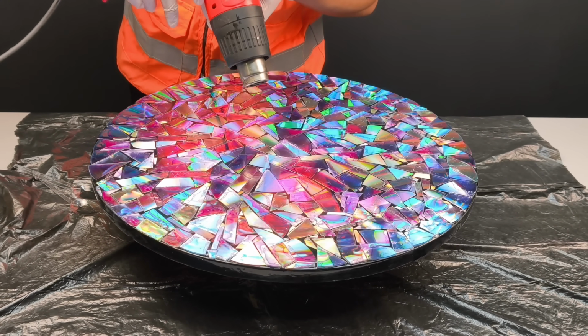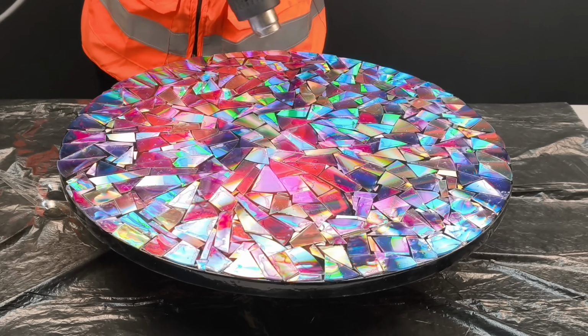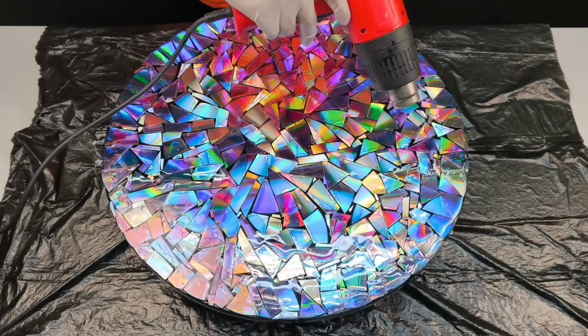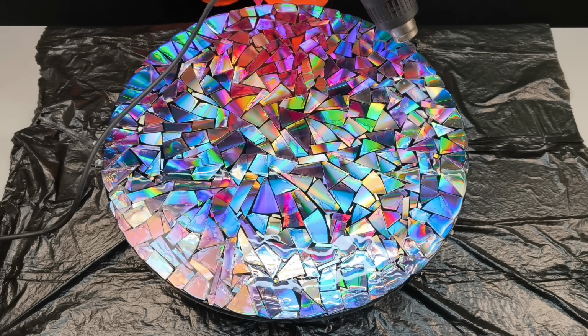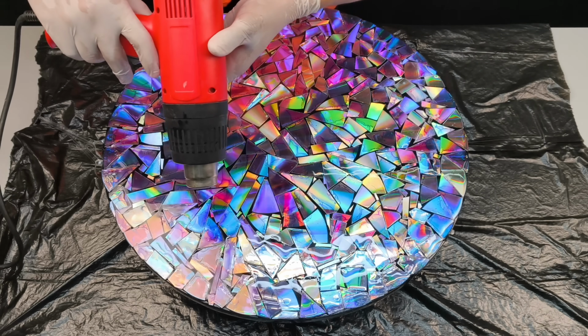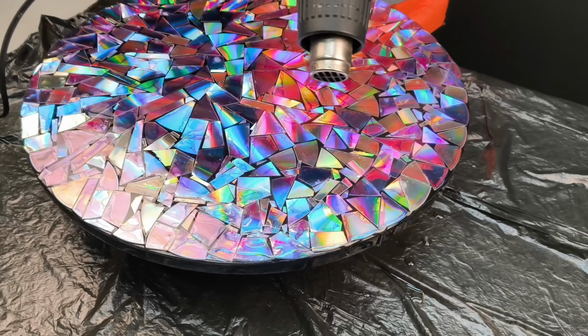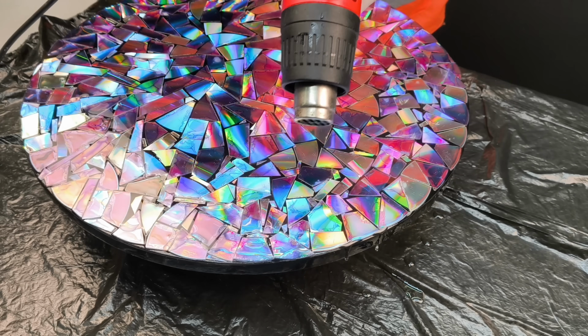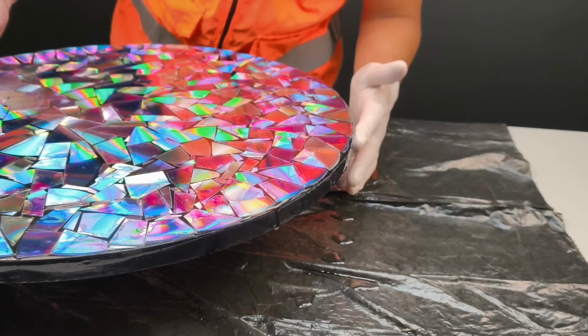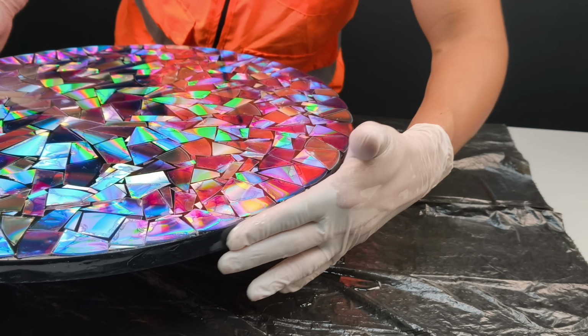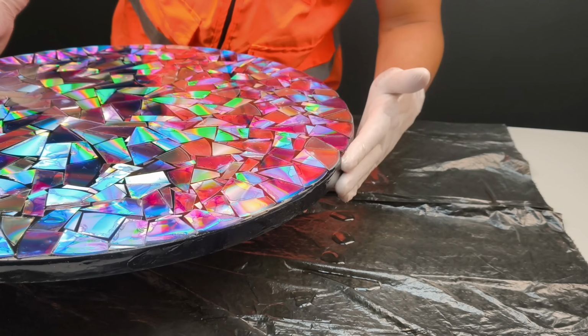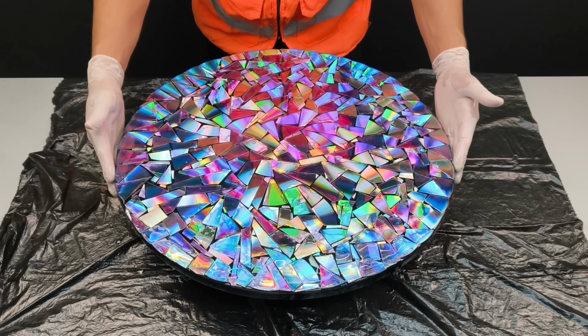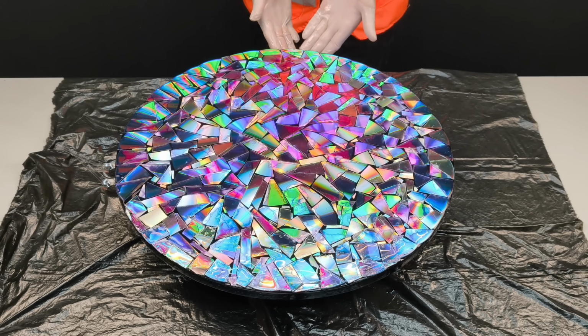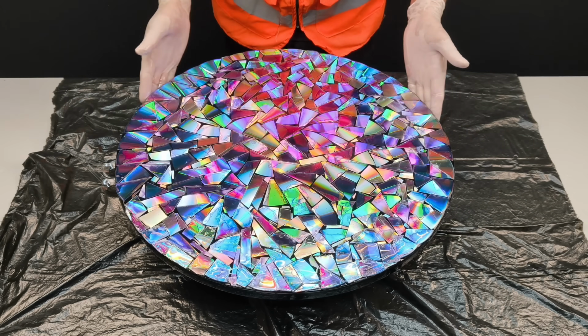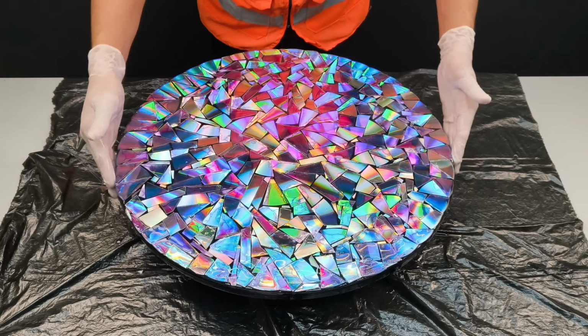After pouring the resin, use the heat gun again on a low setting, keeping a proper distance and constant movement. Direct the heat to help level the surface and remove bubbles, especially in areas where the resin hasn't fully spread yet. Avoid concentrating heat in one spot to prevent compromising the finish. Gently adjust the distribution as needed, ensuring a uniform surface. The recommended curing time is at least 24 hours, depending on environmental conditions, to achieve maximum strength and clarity.